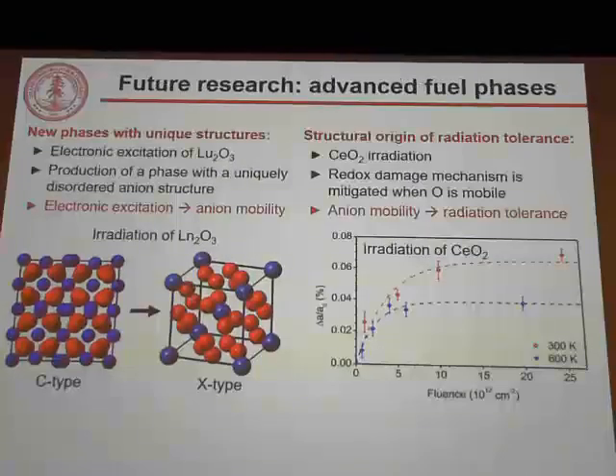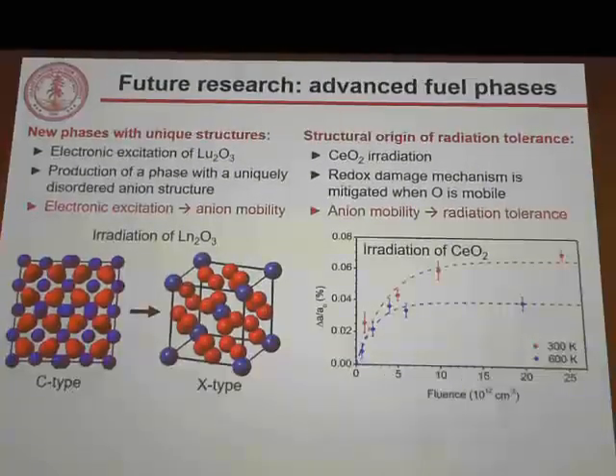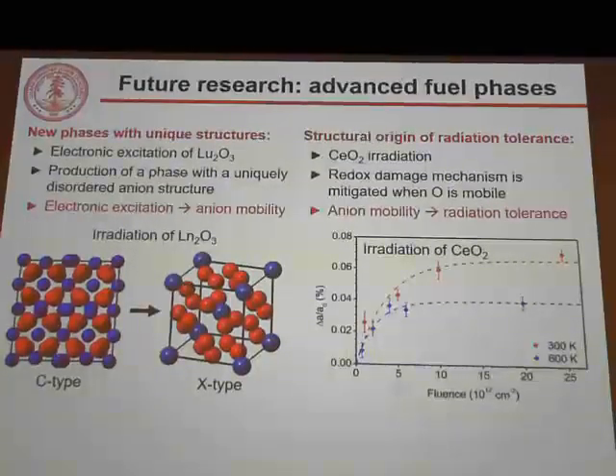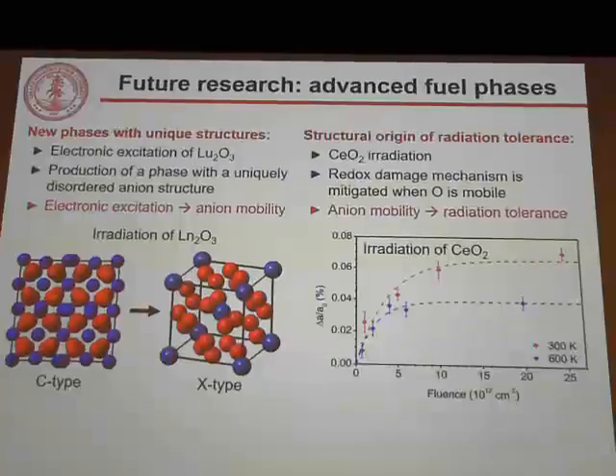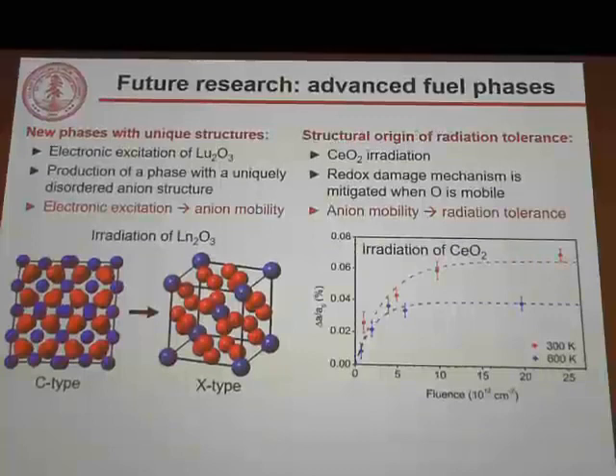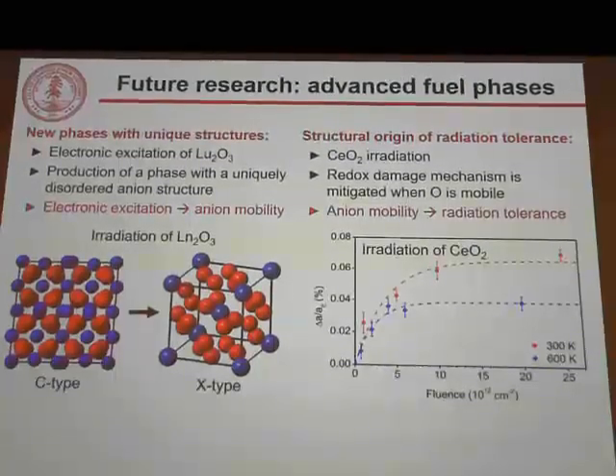So I want to go back to two topics I've talked about. First, on the left, when we irradiated lutetium sesquioxide, we saw that the irradiation-induced electronic excitation yielded extremely high anion mobility, this ionic conductivity in this material. In research I talked about before, when we irradiated cerium dioxide, we saw that anion mobility, or the mobility of oxygen atoms, can mitigate a mode of radiation damage, yielding high radiation tolerance. So we might envision a situation in which electronic excitation or extreme environment processing causes anion mobility, and this anion mobility yields exceptional radiation tolerance that might be superior to that of materials we can access through conventional processing.